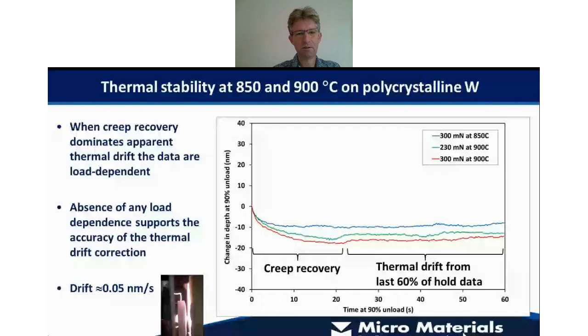So this is an example of how it can work. And in these examples, these are on a polycrystalline tungsten sample tested in high vacuum. And whilst you might think, well, if I'm getting a measurement, how am I really sure it's not creep recovery, and how is it really thermal drift? Well, you can set up tests under different conditions, and if you do that, you can be fairly confident that what you're seeing is actually minimal thermal drift.